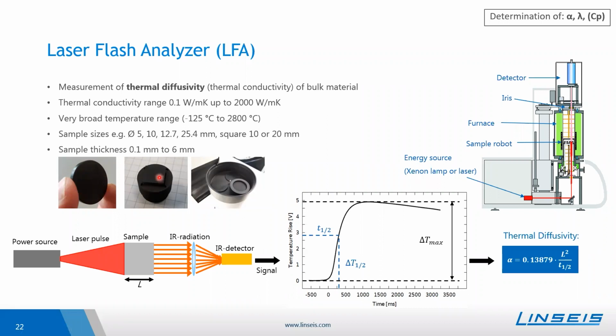And then the sample will be just put into the sample holder and then into the sample robot. The LFA allows the measurement of up to 6 samples at the same time so that there's a high throughput of samples. The method works the following. So you have a power source. This is, in our case, either a xenon lamp or a laser.